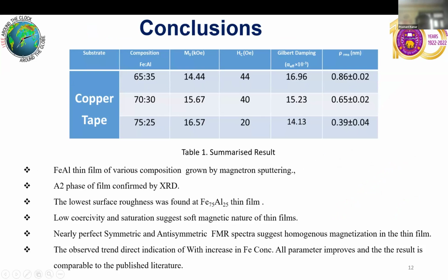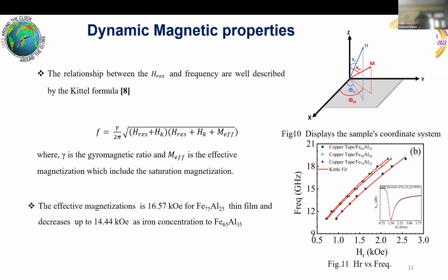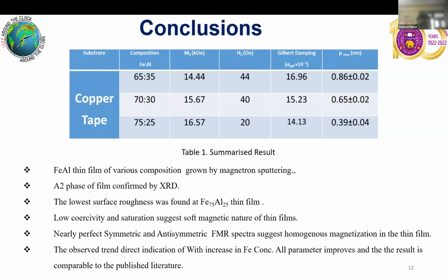The conclusion is that we have fabricated a FeAl thin film with A2 phase. Roughness decreases, coercivity also decreases with increase in iron concentration. And from this graph, we can show that it is an approximately fitted curve, which shows the homogeneity in the thin film.